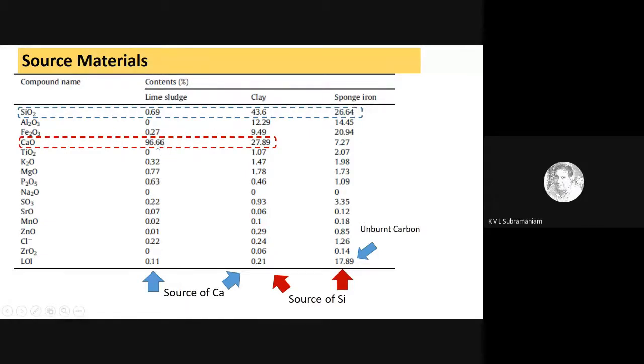And if you look at lime, which is the other key ingredient, most of it comes from lime sludge. So that is good news. Clay also contains some lime. So basically, my two primary ingredients that I'm after are being supplied by these three materials. And then if you look at the loss on ignition, which is basically the heat loss when I burn it to 1000 degrees, it is very high for sponge iron because of all the unburnt carbon that is present there. That means if I put sponge iron with my source material, as it is moving through the kiln, it will burn and produce heat. And that basically can be used to reduce the demand on the fossil fuel for the temperature that I need in my kiln.